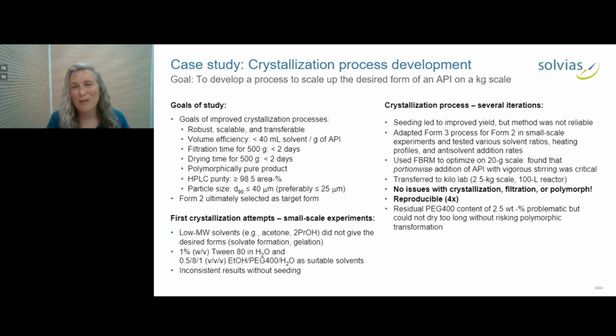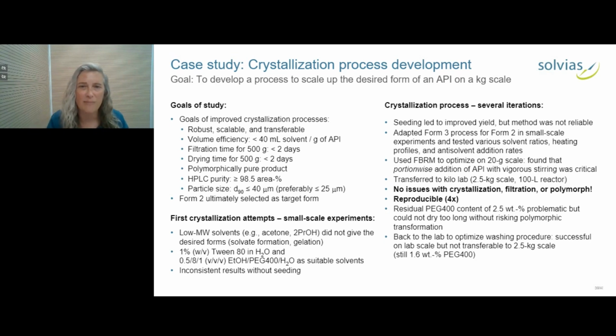The only problem was that there was a residual PEG 400 content of 2.5 weight percent, which was too much, but we had to be careful. We couldn't dry this sample too much because, if you remember, it's a channel hydrate, so we didn't want to dehydrate it and get into another form. So this took us back to the lab where we optimized the washing procedure, looked at different solvent mixtures, temperatures, protocols, et cetera.